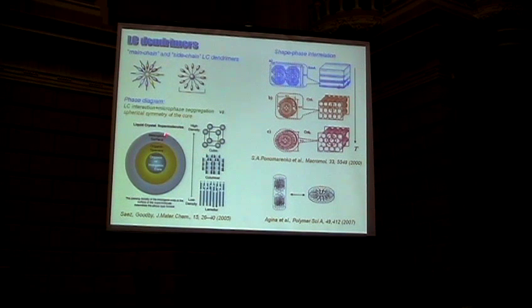In this case we have two tendencies. One is that liquid crystalline groups are interacting one with another, and also there is phase segregation between aromatic mesogenic units and the aliphatic structure of the dendritic core. And against this tendency is the spherical symmetry of the macromolecule.